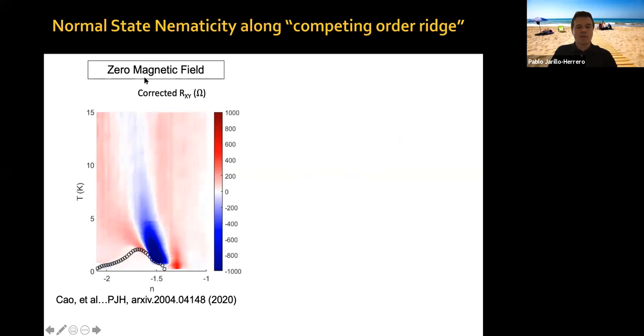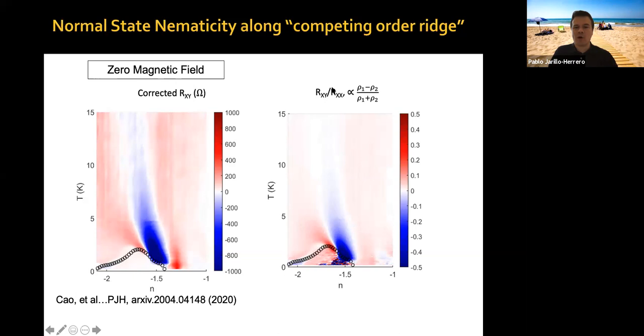So at zero magnetic field, if you measure Rxy, and this is Rxy corrected for any possible effect you would want to account for in order to make sure you're doing a proper Rxy measurement, in particular, we correct for offsets between the Rxx electrodes, etc. You can see that there is this very strong region of anisotropy here, finite Rxy. You can normalize Rxy by Rxx so that you see the true extent and value of the anisotropy. You can see that it's over 50% anisotropy for the strongest values. So it's a very, very strong anisotropy compared with many other materials.